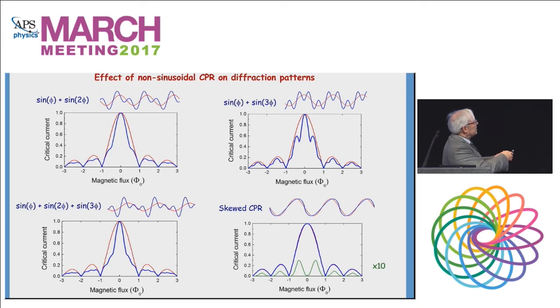But if you look at things like the skewed current phase relation that she was referring to, notice that the superconducting diffraction pattern has not changed very much. This green is actually the deviation, and this is multiplied, in fact, by 10. So it's a very small change. So you want to measure the current phase relation directly, as she was pointing out in the previous talk.